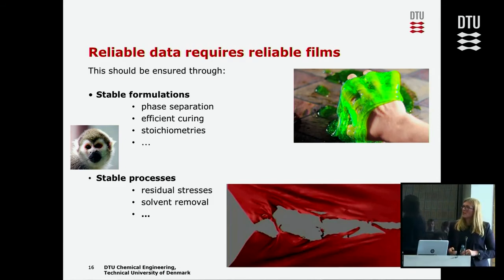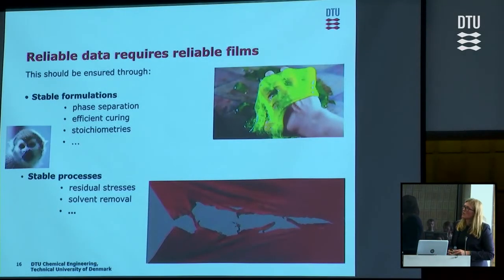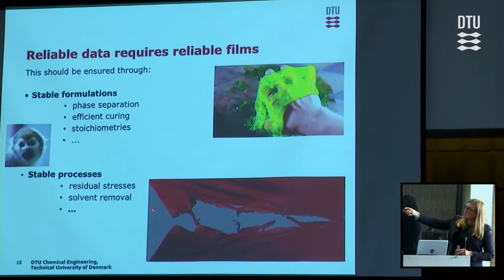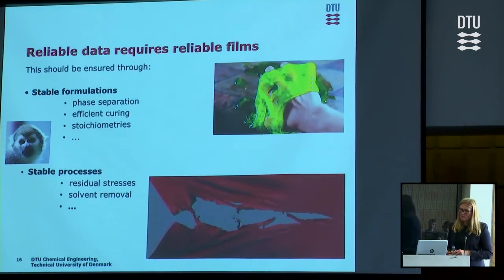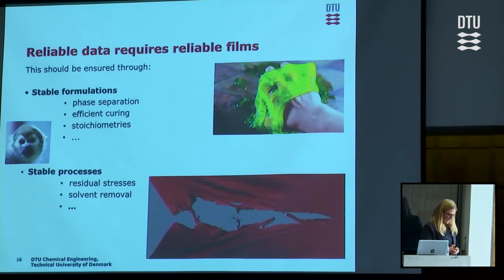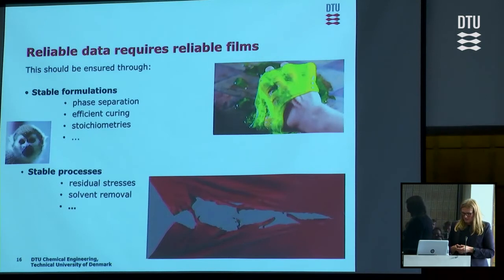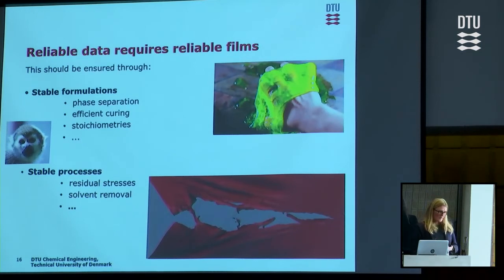Then we proceed towards the stable processes, and there it's very important we don't build up any residual stresses when we coat our films. And as I also talked about, especially for the composite, we need to be sure that we get all solvent removed. We can see that with a few percent of solvent remaining in our elastomers, we really get a significant change. I showed it in the Young's modulus, but also in the electrical breakdown strength. And if we, for example, take our films, coat them and make them into products immediately, then of course the solvent will never really have a chance to leave the product afterwards.